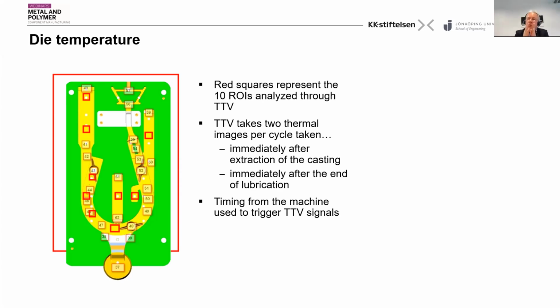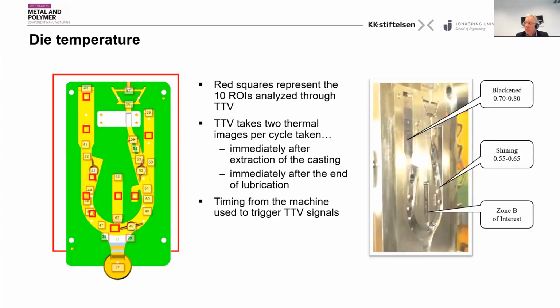And then for control of changes, maybe you only need 1, 2, or 3 areas of control, not so many as we used. Of course, if we are talking about infrared, there are a lot of things to control. It's not a Lambert radiator. Some areas are more black, others are more shiny, so you get different temperature readings. But that's not really the problem, because you only want a relative signal to the shot before and the shot after. So I think you can use this very nicely.